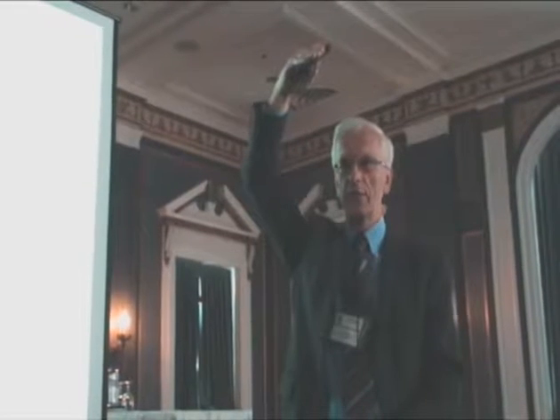What happens is that this hole here is being filled by electrons in higher orbitals. So an electron falls down and fills this hole, and you're left now with a hole up here. This is much more shallow, so this is just 1 or 2 kiloelectron volts. So the uncertainty principle tells you, Heisenberg, the old Mr. Heisenberg tells you, that now the lifetime is much longer. So the line width is much shorter. And that's what we see.